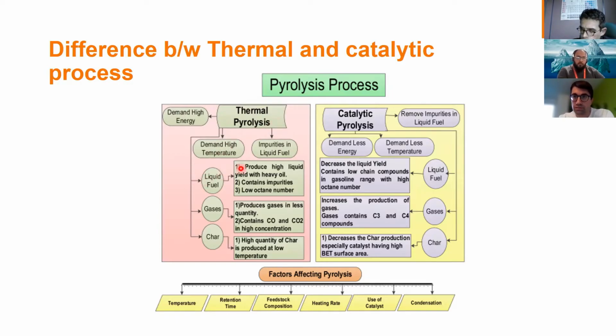The liquid fuel can contain impurities, can be of low octane number, but on the other hand, it produces high liquid yield with heavy oil. The gases from this pyrolysis are produced in smaller quantities, but can contain carbon monoxide and carbon dioxide. The char from this process can be in high quantities, even at low temperatures. But if you use a catalyst for the same process, you have the possibility to remove impurities, because the catalyst can also act to absorb some of the impurities. It also means that you would require less energy for the pyrolysis, because you need less temperature for the same degradation.